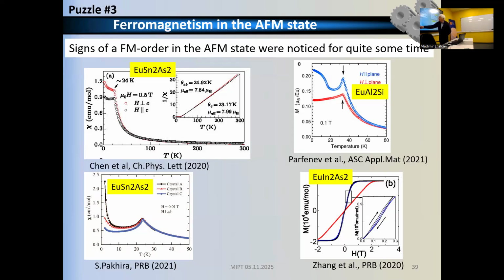For example, if you take measurements of the magnetic susceptibility, you see that below the magnetic transition temperature, it should stay constant in one direction and drop down to zero in another direction. Instead, it diverges. And this is in a paper where authors specifically studied how to grow the sample with the highest quality in order to avoid this. All of the experimental studies exhibit signatures like this, and even some exhibit signatures of very weak hysteresis in DC magnetization curve, which of course is not intrinsic to antiferromagnetic materials.